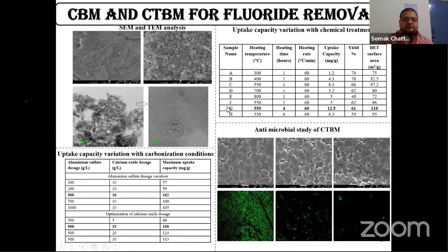So as we were able to make this one, we then went on to the uptake capacity variation with chemical treatment. So how did we do that? First of all, we have aluminum sulfate dosage variation. When the dosage was increased from 100 to around 500, the uptake capacity also increased to 102. Now at 500, we were seeing this part is nearly getting saturated.